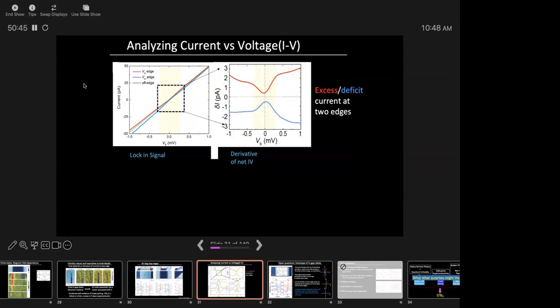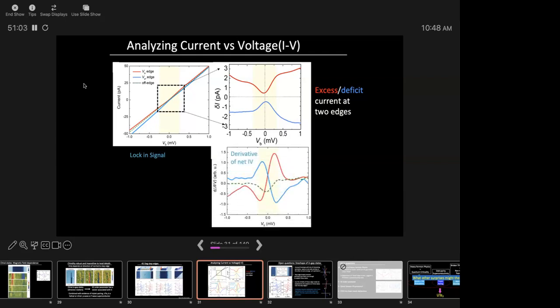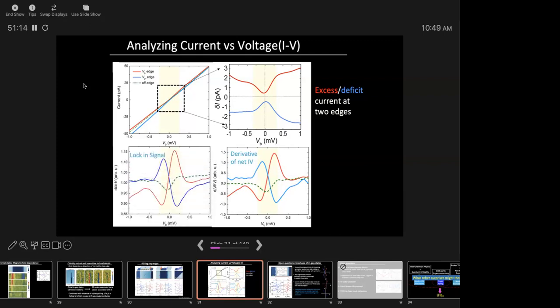On one step edge, the IV looks like this, and on the other it looks like this. What this is telling you is that depending on the step edge, no matter what your bias voltage is, you either have excess current or less current. And this funny feature in the IV is exactly what gives you the signal. This is the derivative of the IV. You see these two peaks have to do with this funny gap-like feature in the IV. And this is our lock-in signal exactly at the same position.